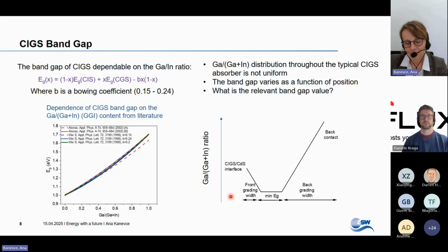The other thing is that many of the CIGS solar cells are made with spatial non-uniformity. This is so the gallium content, and therefore the bandgap, in a region is smallest. This is made to optimize the short circuit current density, and then it's larger in the front and in the back. This is to optimize VOC, and there is almost always back contact grading to minimize back contact recombination, as well as for low quality cells to provide a back surface field.